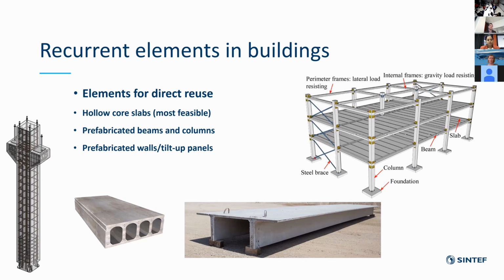But the horizontal elements, like hollow core slabs, are not as sensitive. The live loads in structures are quite similar from one building to another. The range is between 2.5 and 5 at most in office buildings. So this makes them a good candidate for reuse. So we were focusing on prefab hollow core slabs. And the problem here was the removal of the overlay, the top surface.